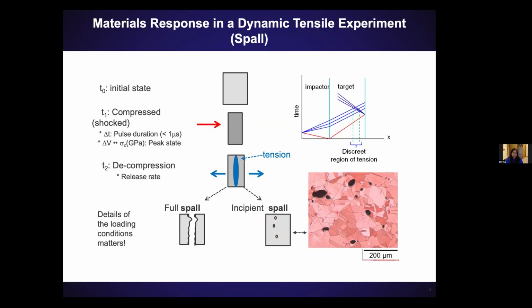And if you were looking at a material under the microscope after you've picked it out of the gun, you sectioned it and you prepped it, what you would see is these voids kind of located at different features in your microstructure. So this, I think, was copper, if I remember correctly. You can see different grains here, and you can see a lot of these voids are located at grain boundaries and triple junctions within that region of tension. You don't just get damage all over the material, just in a narrow band.